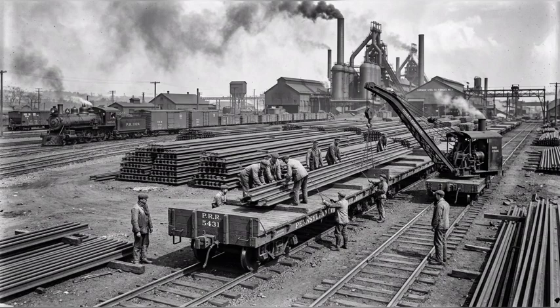At the base of the furnace, tuyères, iron nozzles arranged in a ring, blasted preheated air into the combustion zone at pressures exceeding 45 pounds per square inch. This superheated the interior to approximately 2,800 degrees Fahrenheit. At that temperature, iron ceased to be solid, ceased to be predictable, ceased to behave like anything a man could safely approach without full awareness that one failure in the system meant instantaneous death.